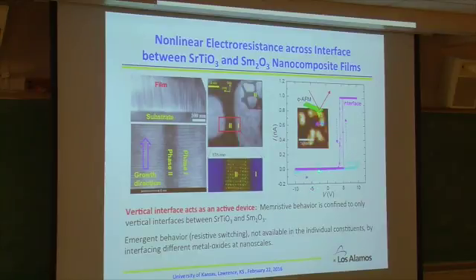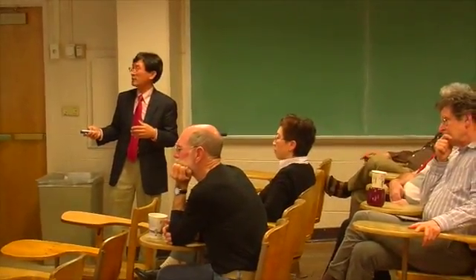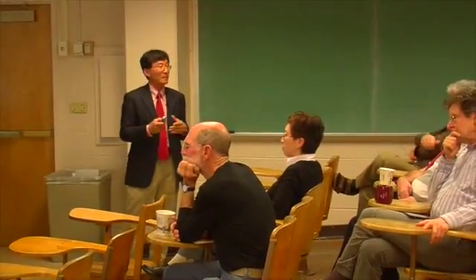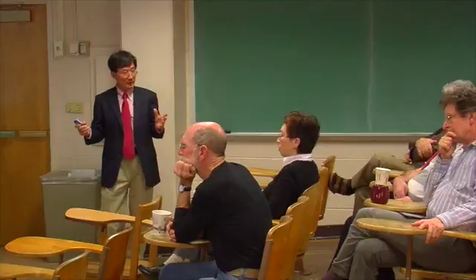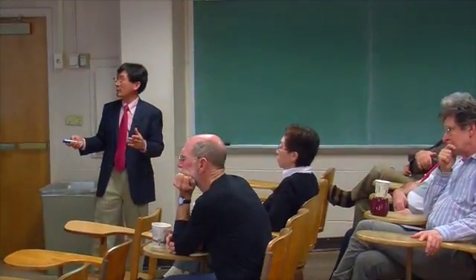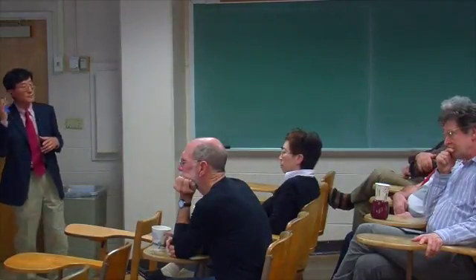A very good question. I believe over here, that's due to the non-symmetric electrode. You probably also have the Schottky effect, the barrier effect as well, potentially. So we don't know exactly, but that's a very, very good question. So basically over here at 10 volts, it's not on. Over here at less than 5, that's on. Since that's not symmetric, you think about this. The bottom electrode is niobium doped strontium titanate. Here on the top, you have this AFM tip. That's potentially another reason.